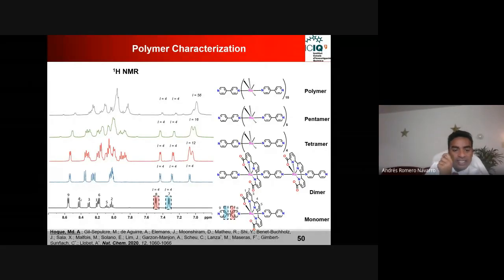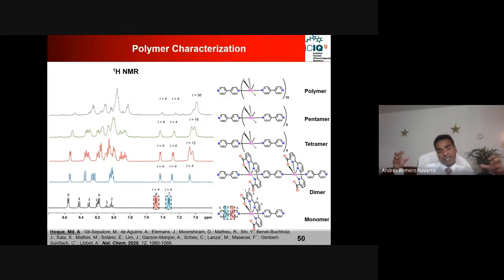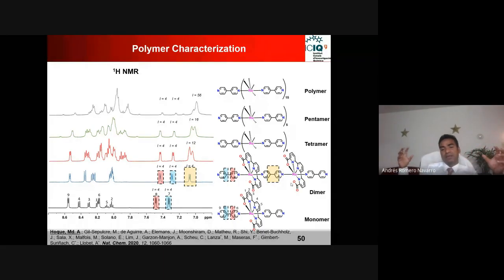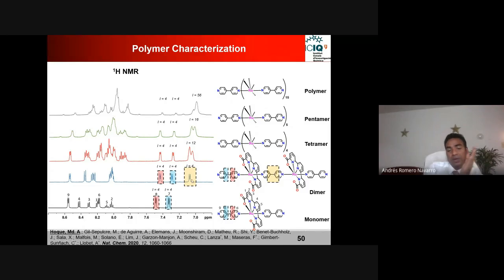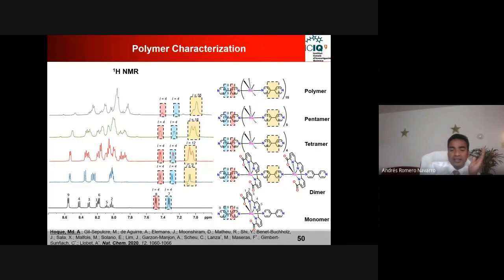So now here I'm showing the NMR of this mononuclear compound. You can see that these two signals are related to this terminal bipyridine ligand. Once you move from mononuclear to dinuclear, you will have one of these as a bridging bipyridine ligand, right? So in the dinuclear compound, you have 2 different kinds of bipyridine ligand, because the other will be almost identical. And when we have this bridging bipyridine ligand, we found that it has a signal at a lower ppm value than the terminal one. And now we can see that the relative integration of these signals is increasing with respect to this terminal bipyridine.